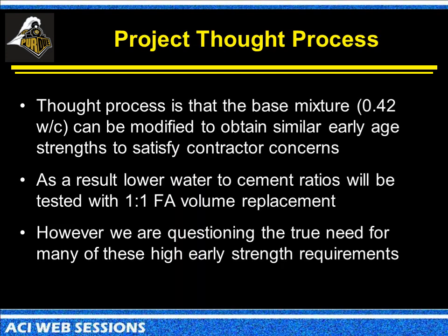So our thought process behind this, and I'm not going to go through this in great detail, is to start off with the baseline mixtures that are used in a lot of states, where we're at a 0.42 water cement ratio. We'll be looking at replacing the cement 1-to-1 with the fly ash, keeping the same volume of the overall paste in the system. And the first thing that we kept hearing from people was the issue of early strengths. One of the ways that we can come at looking at these early strengths is to alter the water to cement ratio at the early ages. So that's really what we're looking at.